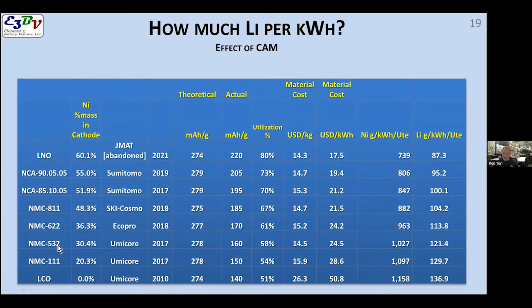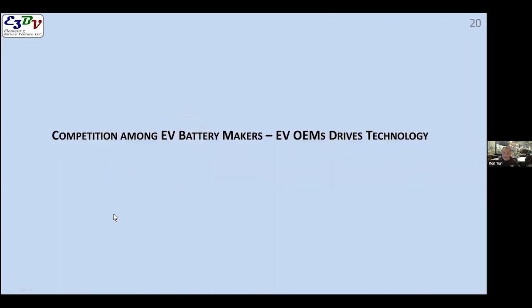And that's why you see the amount of nickel creeping up from one third, this would be a 3, 5, 6, 80%, and now 85%, 90% nickel. And when you do, the milliamp hours per gram, milliamp hours being capacity per gram of cathode, go up. And your utilization of the material, the utilization of the lithium, the charge in the material, keeps going up. And effectively your price, which might go up a little bit on a kilogram basis, goes down overall when you start multiplying it into a USD per kilowatt hour basis. So there are some real advantages to advancing the chemistry.